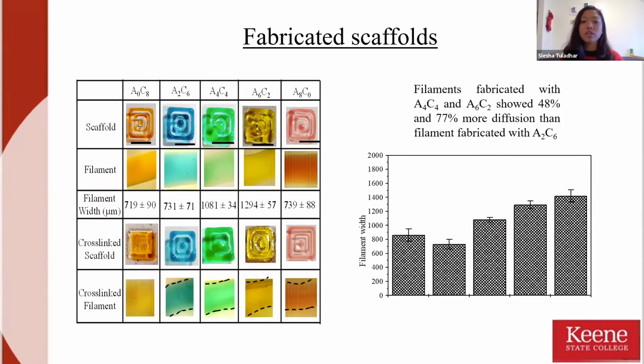So these are the results of the printed scaffolds, and we can clearly see that A6C2 is showing a lot more diffusion than other scaffolds. Also, the filaments fabricated with A4C4 and A6C2 showed 48% and 77% more diffusion than filament fabricated with A2C6, respectively.